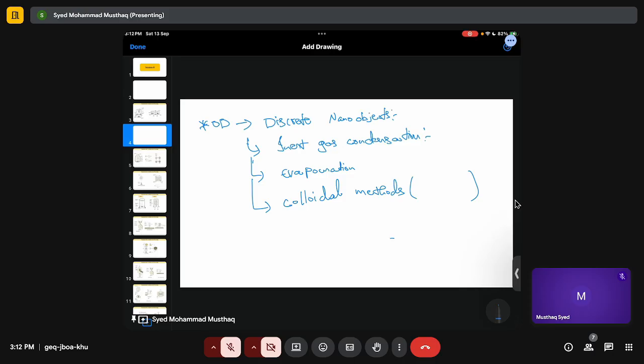Okay, so for example, if I have a nanoparticle and then I attach some citric acid or some other polymers, even I can attach a citric acid membrane, and for example, if you form Fe3O4, the citric acid will attach to this Fe3O4 and it will make sure it will not coagulate or form agglomeration. So these chains will make sure these nanoparticles do not agglomerate. So another thing is doing the colloidal solution.